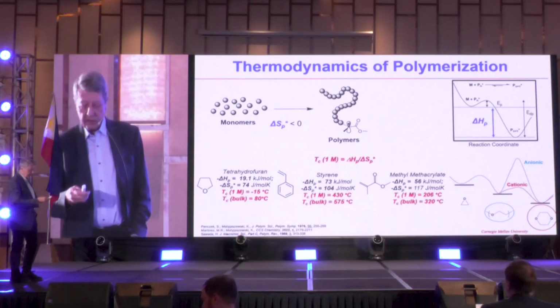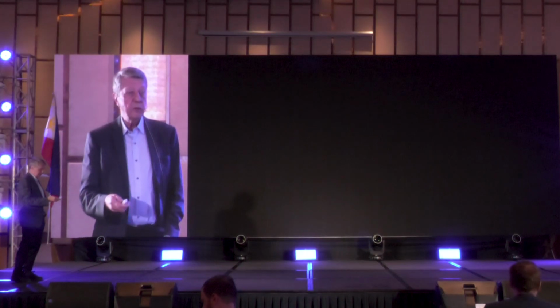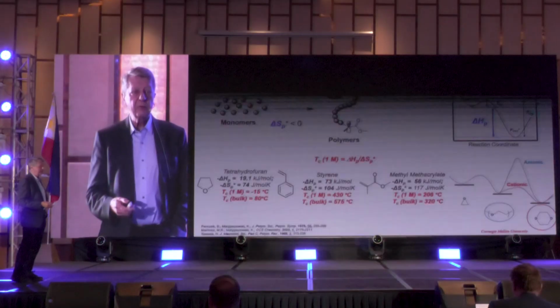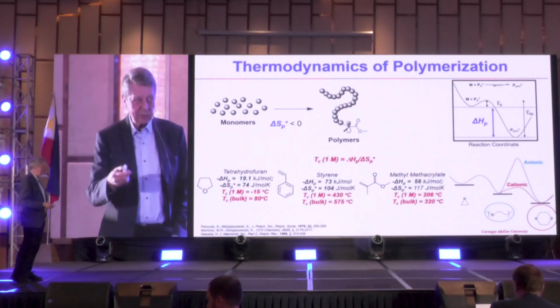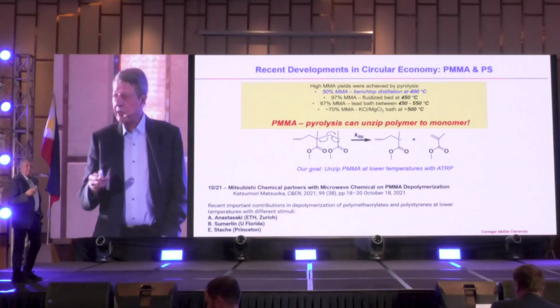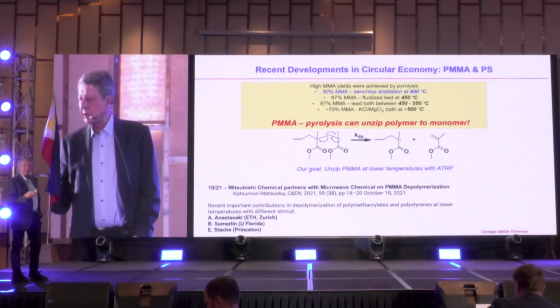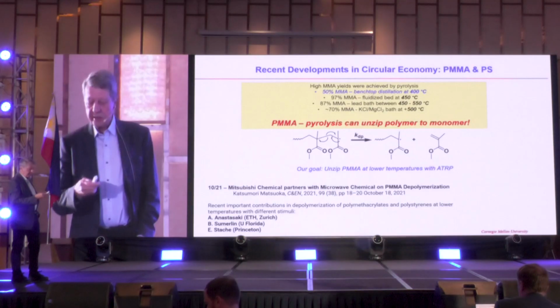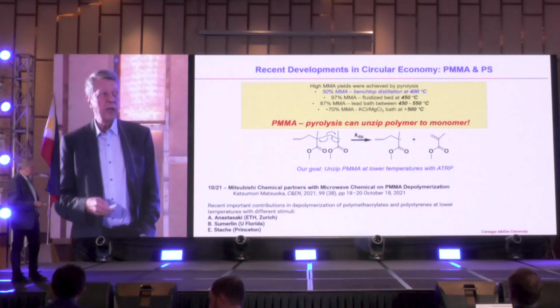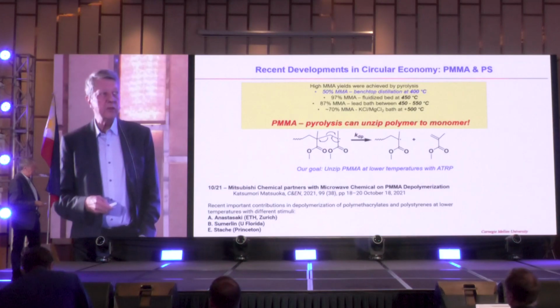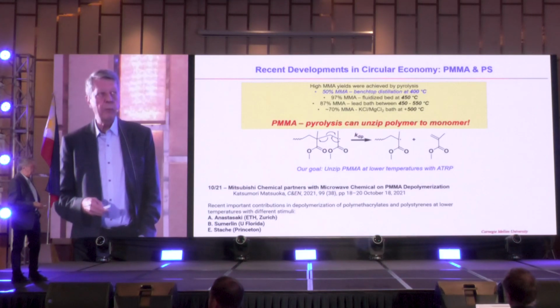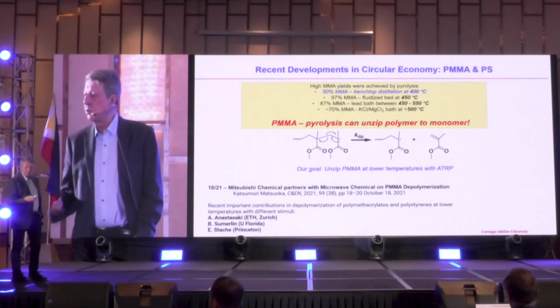So one example is shown here, which is, okay, I think I need your help again. Next slide, please. If you take polymethyl methacrylate, plexiglass, plexiglass can be converted back to monomers at temperatures in a range of 400, 500 degrees. So can we do it at lower temperature? Can we do it through this living polymerization? And in that case, you can depolymerize polymethyl methacrylate back to methyl methacrylate and make new polymers again.